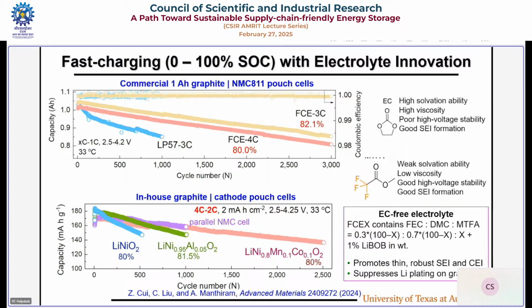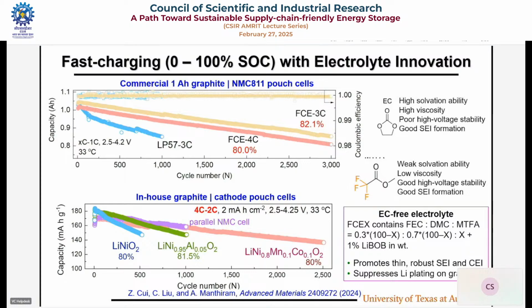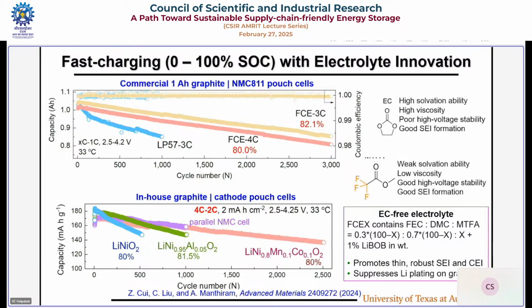This is a cell made in our lab, similar. The electrolyte plays a much more dominant role for fast charge and cyclability, for everything. Electrolyte is a forgotten thing. We thought, yeah, it's a little thing sitting there transporting ions, but it is not. The electrolyte is much more dominant. If you have a good electrolyte, a bad cathode or a bad anode can work better.